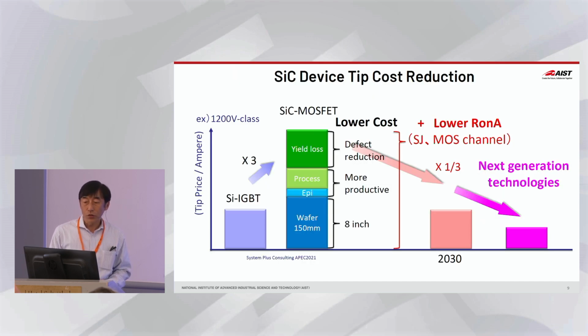Regarding the chip cost reduction, for example, for the silicon carbide MOSFET, the cost compared with the silicon IGBT at 1200 volt class is roughly 3 times. The largest component is wafer, and then yield loss, process, and epitaxy. So to reduce the chip cost, at least an 8-inch wafer is necessary, and also a more productive process and defect reduction in the epitaxy layer are necessary.